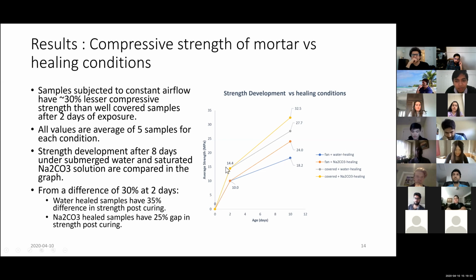So this is the damage part. And then I leave them under different conditions of healing. Since it is early age, there is continuous hydration going on, as well as the extra curing that we are providing. So as we can see in both the cases, there is a rise in strength over age. And this is the difference between sodium carbonate and water healing. If we subject the sample to sodium carbonate, it is having a higher strength. Even in this case, it is having a higher strength.